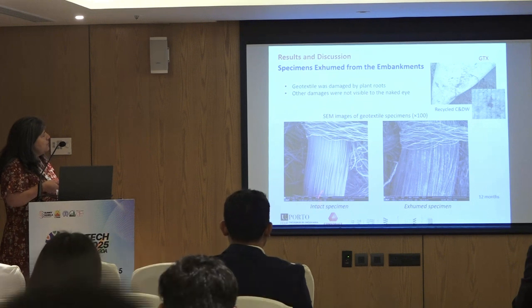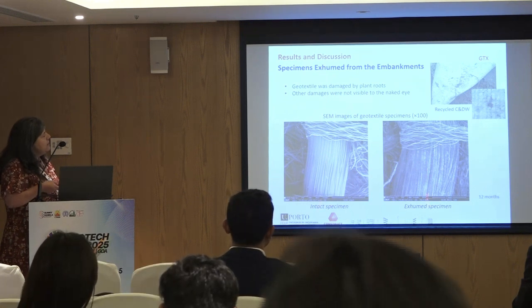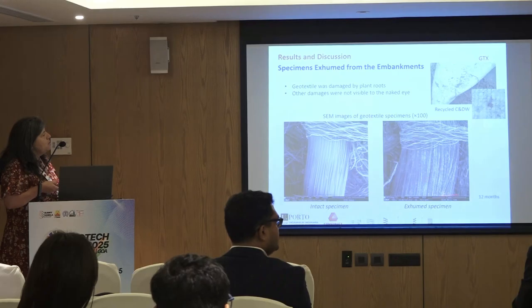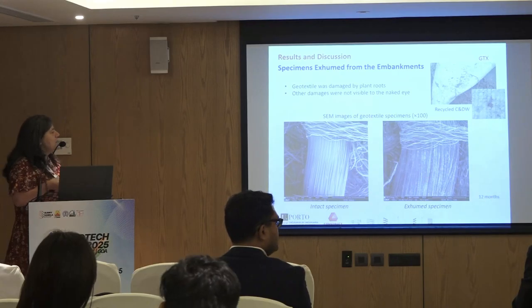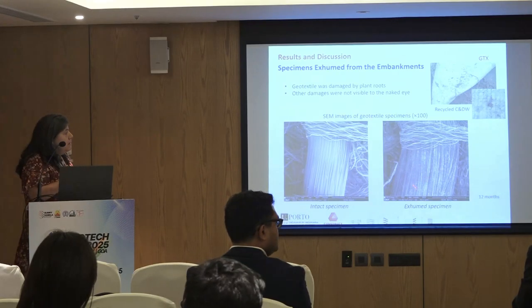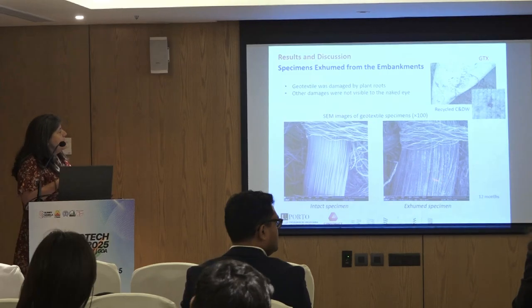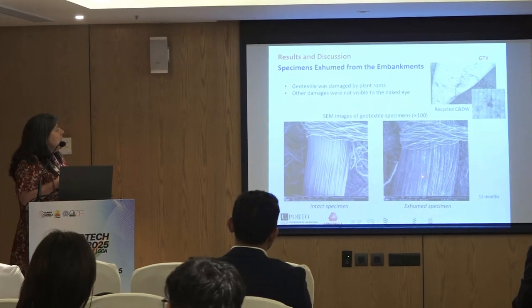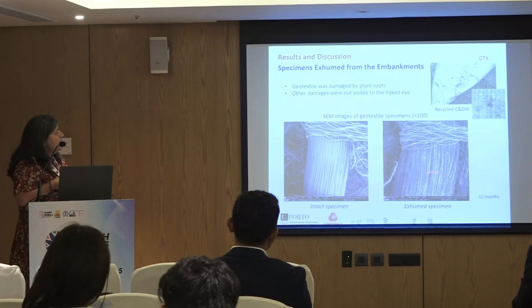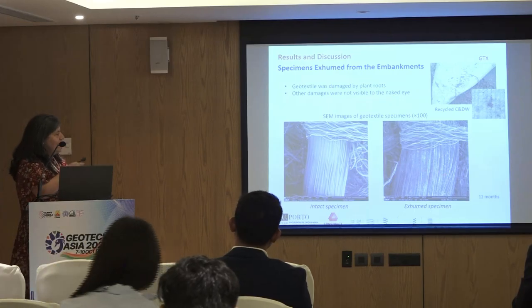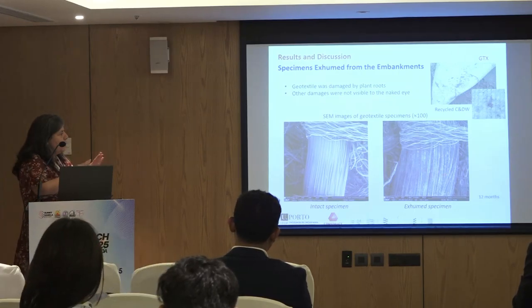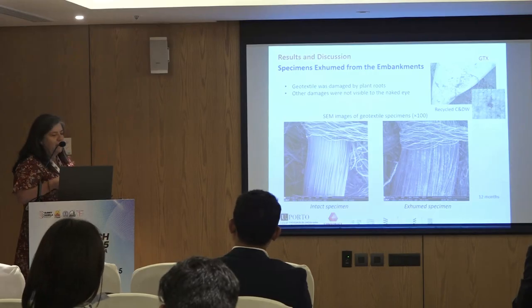This image refers to intact specimens, and this one to the specimens exhumed after 12 months of exposure. And we don't see any kind of damage, as expected, in the polyester yarns, even if they are less aligned. They are more spread in the geotextile.